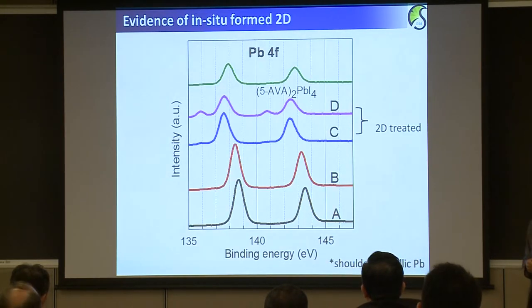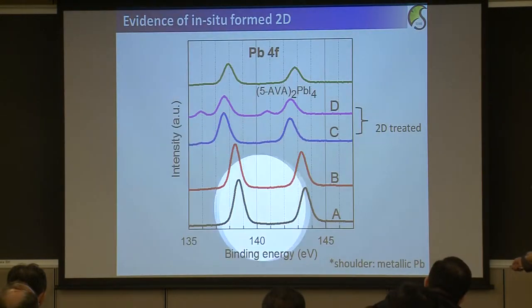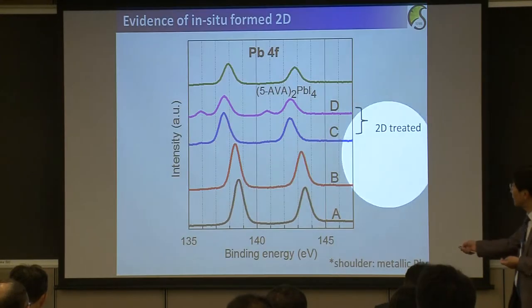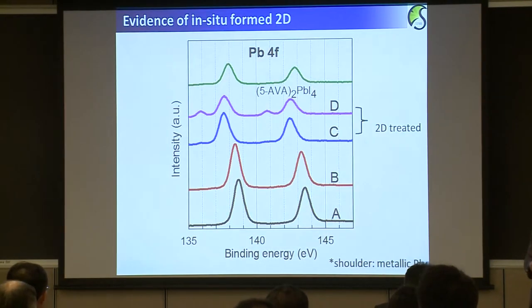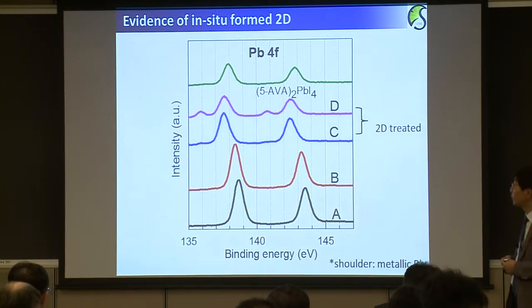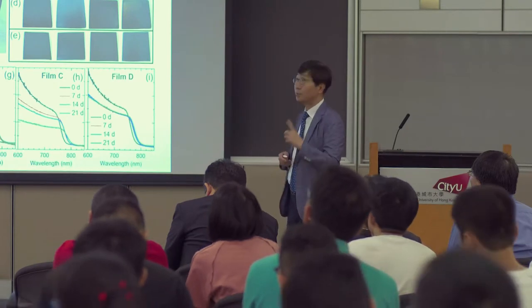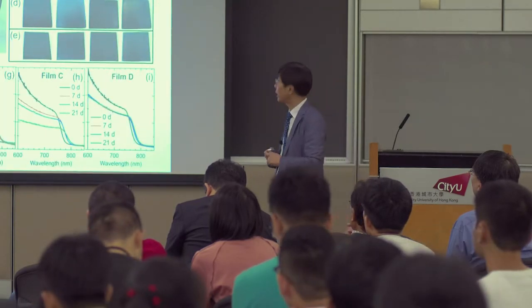And also we confirmed the presence of the two-dimensional layer by using XPS spectroscopy. For instance, for the pristine compound, you see the Pb 4f XPS peak here. And then after treatment with the two-dimensional structure, we found that the Pb peak is slightly shifted to lower energy, which is indirectly confirming the formation of the two-dimensional layer in between the copper thiocyanate and the perovskite. And also, with this method, we tested humidity stability, and we found that the two-dimensional structure shows pretty good tolerance against the humidity.